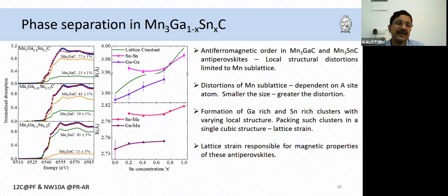So we did this for the entire series at Photon Factory on beamlines 12C and NW10A, the gallium edge, the tin edge, and the manganese edge. Everything was done at these two beamlines, and right through the series, we could see what you call phase separation, which can be seen here also. Here I am plotting the gallium bond distance as well as the tin bond distance, and both of them, these are basically lattice parameters, show a very different behavior. And this green curve here is the way the lattice constant varies across the transition.